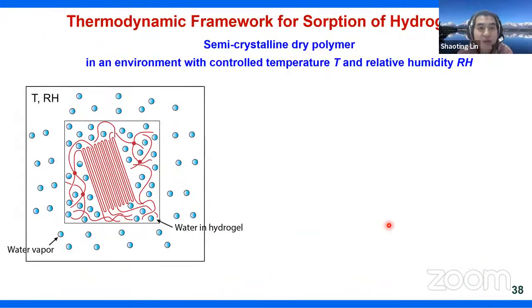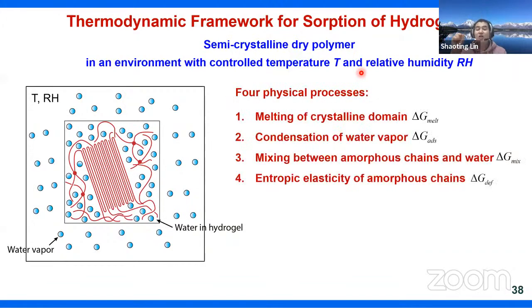So we first developed this thermodynamic framework, trying to understand this physical process at a controlled temperature and a controlled relative humidity. Basically, there are four physical processes. In addition to the mixing between the amorphous chain and water, and the entropy elasticity, which are covered by this Flory-Rehner theory, I also include two other terms. One is the melting of the crystal domains, and the other is the condensation of water. Basically, we need to account for this phase change in the system. This is different from swelling.